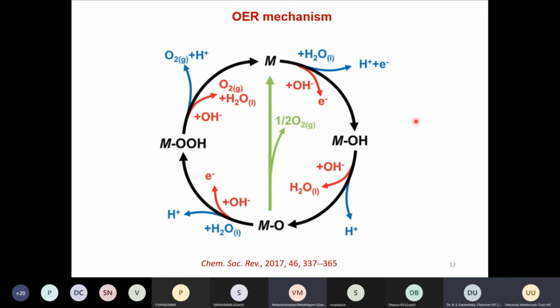But if you see the oxygen evolution reaction, which is the counter reaction, it's a very complicated process because it involves 4 electron proton transfers. For example, if this is a metal which is a catalyst, in the presence of water there is an H plus and electron release, which leads to MOH. First, it forms a metal hydroxide, and this metal hydroxide can form metal oxide by again releasing a proton and an electron. And this metal oxide can directly go to the metal by release of oxygen, or it can again react with water to form a metal oxyhydroxide species. Then again with one more electron and proton release, it will become metal. Again, the metal is released and oxygen is released.